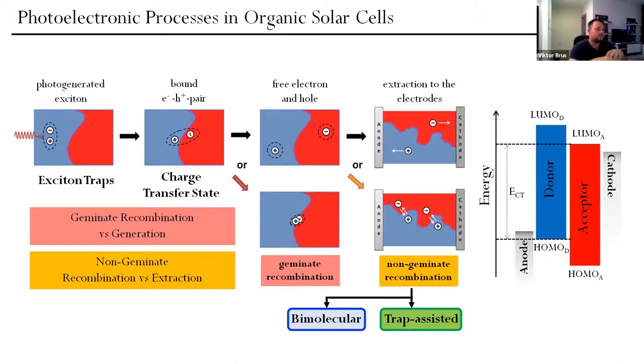So first, these domains of donor and acceptor could be too large, for instance. If they are too large, there is some limited diffusion length of the exciton. It is from 10 to 20 nanometers, and they need to reach the interface of donor and acceptor in order to split. If within this diffusion length they don't reach the interface, they will just annihilate and this exciton will be lost.